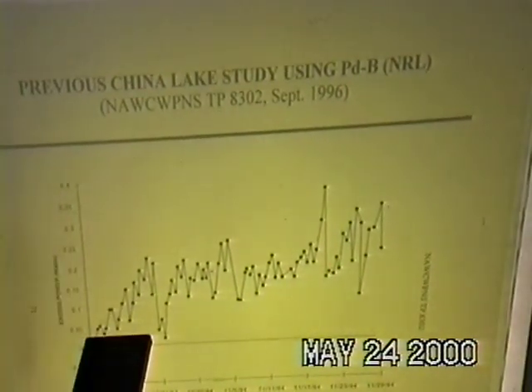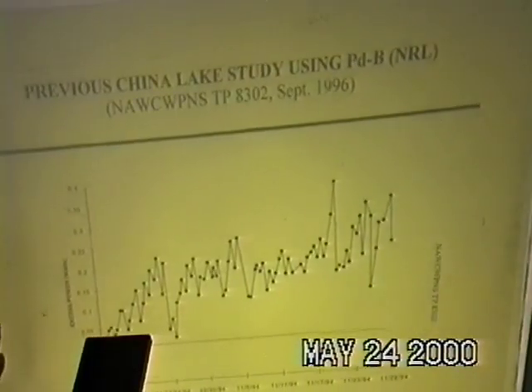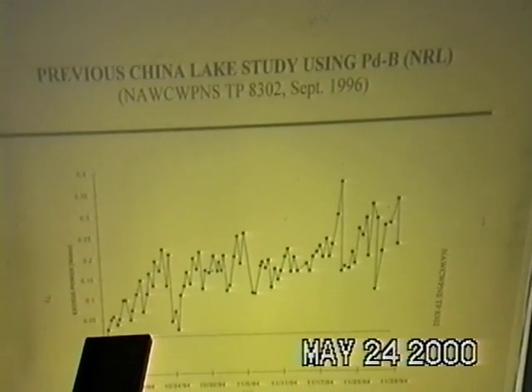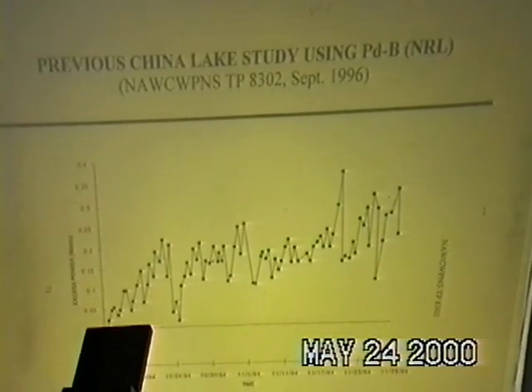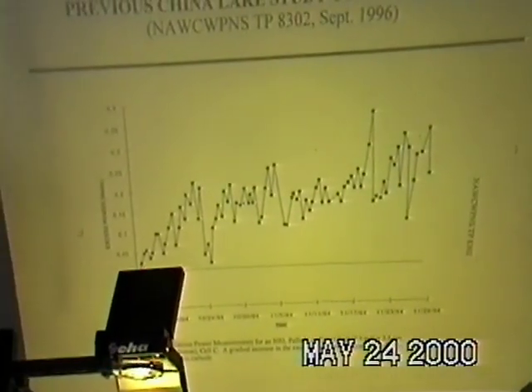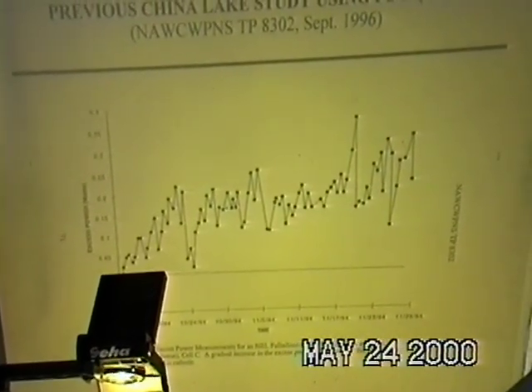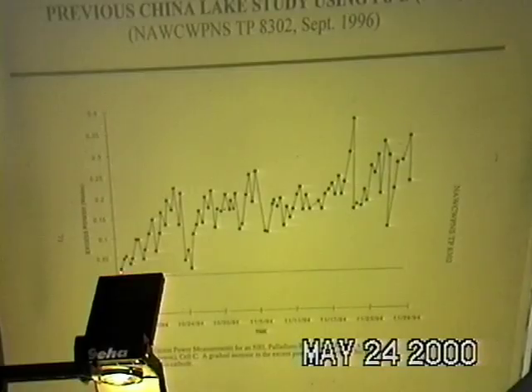This is an earlier study on palladium boron. This was done at China Lake. One interesting feature shown here is excess heat starts very early, almost right at the beginning of the experiment, almost the first or second day. Excess heat starts to appear. We see this also in the results in Japan. Excess heat sets in very early in this palladium boron experiment.